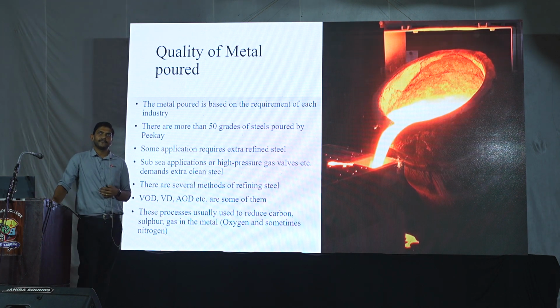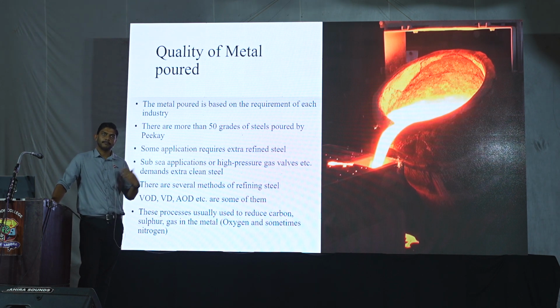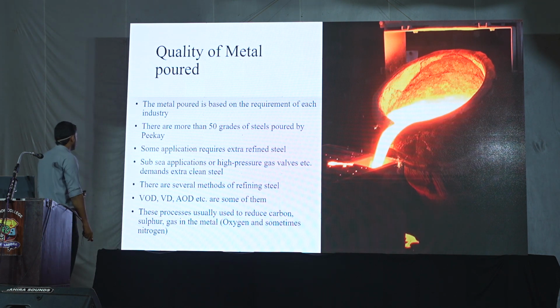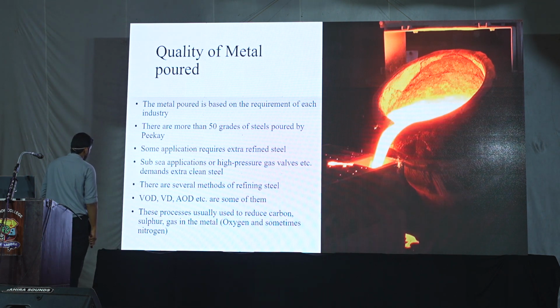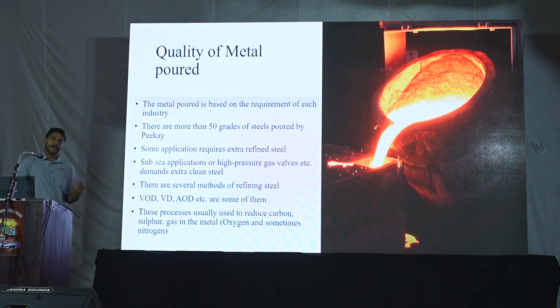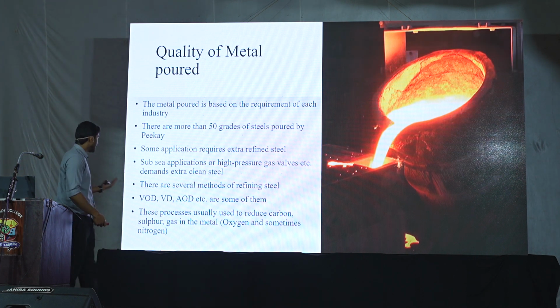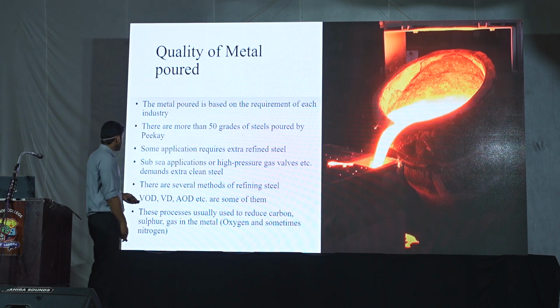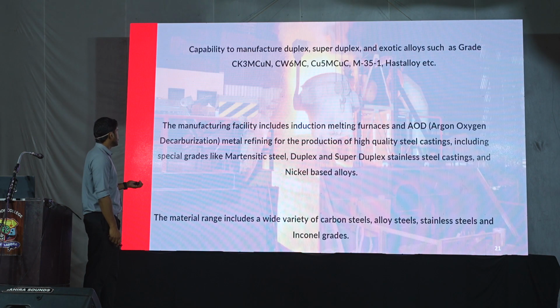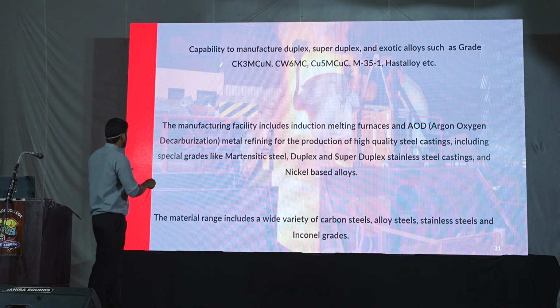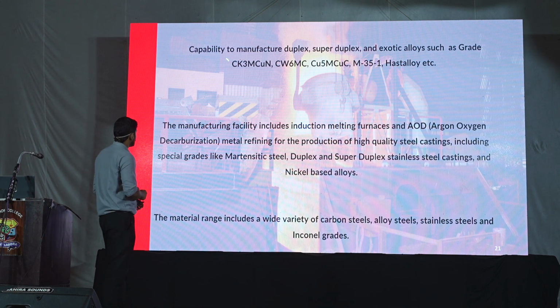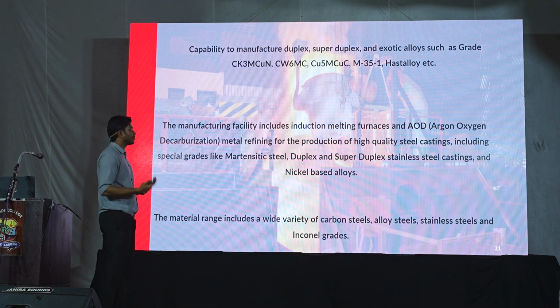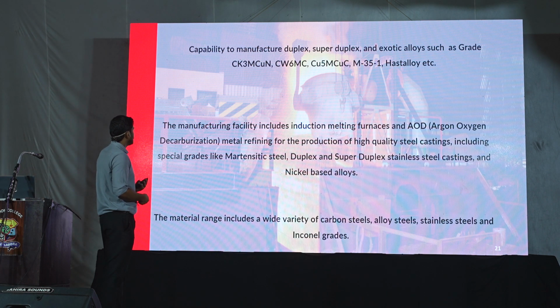This is also at least a 5-decade-old technology, which through time got refined better, and one of the best forms of that we are using currently. It is called argon oxygen decarburization, or AOD. There are also vacuum oxygen decarburization and vacuum degassing. In our terms, these are all ways in which we represent materials. This is basically a superaustenitic stainless steel, which has around 20% chromium, 6% moly, and 27% nickel.